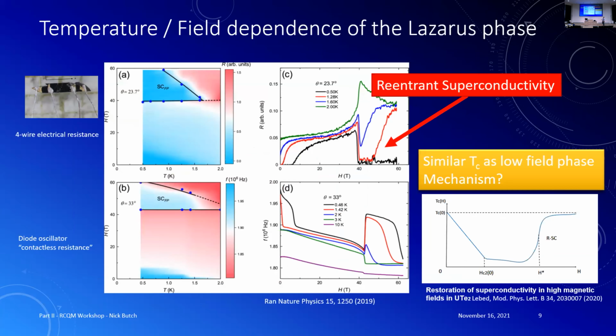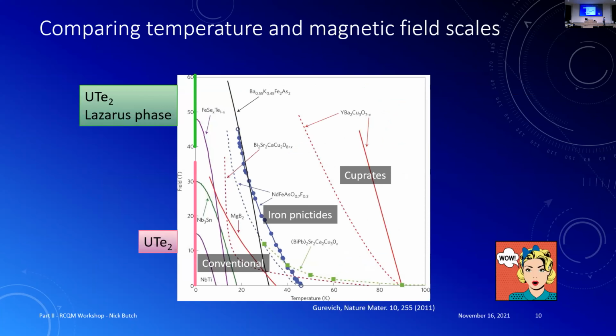And so if one wants to look at an HC2 curve for that phase, here we go. So this is resistivity, and this is probably a proximity diode oscillator measurement. But both of these show here, resistivity goes to zero. It's got the right temperature dependence. If I plot this, TC looks comparable to the low field state. It's always a question when you find superconductivity at these fields, what's going on? And so that's an open question.